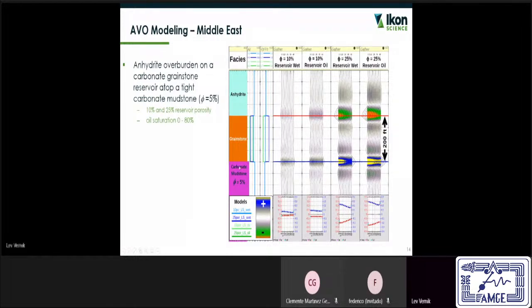And then on the base, it's underlain by carbonate mudstone, very tight carbonate mudstone with 5% porosity. So we vary porosity from 10% to 25% in these specific displays of AVO synthetics. And we model wet responses, which is here and here, versus oil responses, which is track number 2 and 4. So you can see that various scenarios of porosity and fluid saturation can be very successfully modeled using this approach.